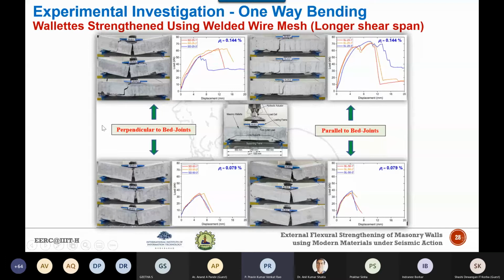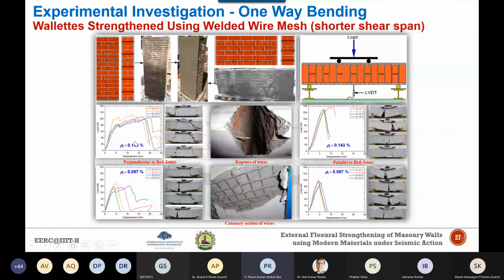See, here the reinforcement ratio is 0.144. Here also the reinforcement ratio is basically 0.144. Here the failure pattern, if you see, is either diagonal shear cracking or sliding shear. Now here you can see that they have been converted into flexural failure. So by simply changing the shear span to depth ratio, the failure modes can be changed.